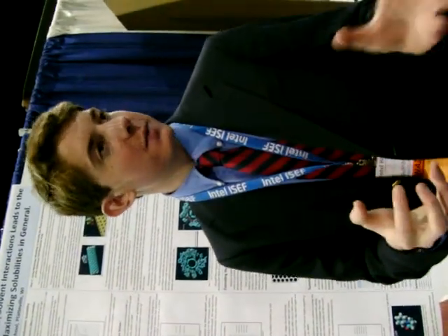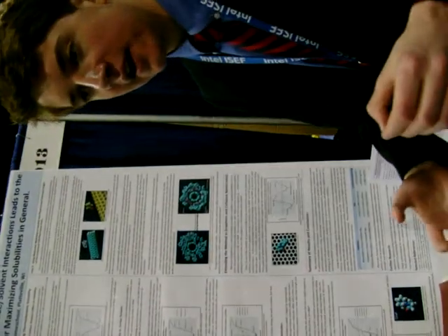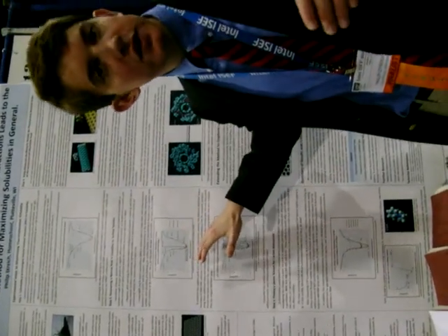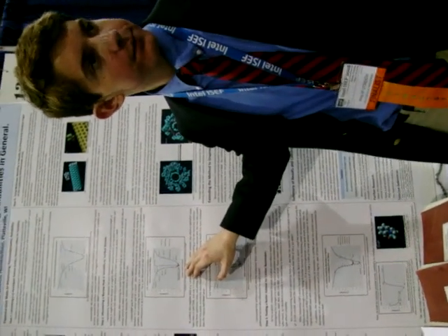Yes. So in my research this year, I set out to maximize the thermodynamic solubility of carbon nanotubes. And in the process, I discovered a new method for maximizing solubilities in general through a fundamental connection I uncovered between solubility and the actual surface tension of the solvent. And this method lets you systematically mix different solvents together to reach an optimal surface tension that then maximizes solubility.